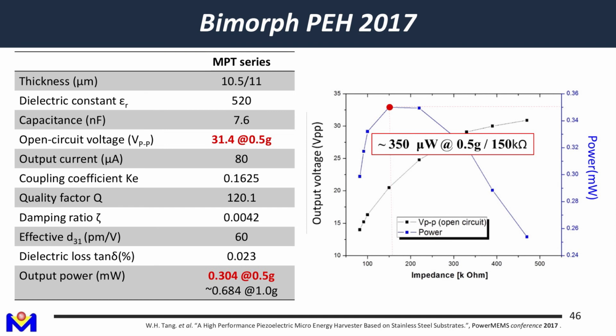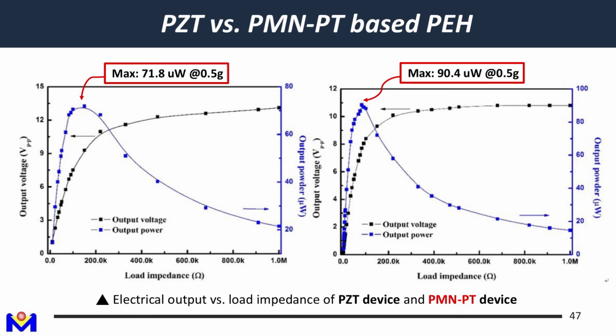So if you want to optimize for a lower acceleration level, generally speaking, you have to have a less stiff cantilever beam, so we can generate larger deformation at a lower acceleration level. So it's again about the optimization, different targets of optimization. And we also tried PMN-PT, which is supposed to be a better piezoelectric material with a higher piezoelectric constant. You can see with overall the same geometry parameters, we can get a little bit higher power output compared with PZT.